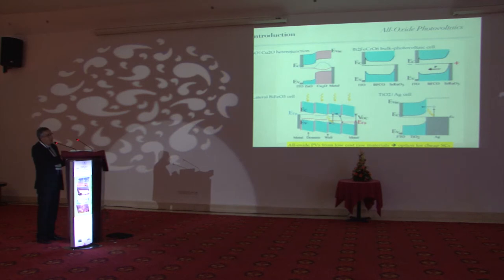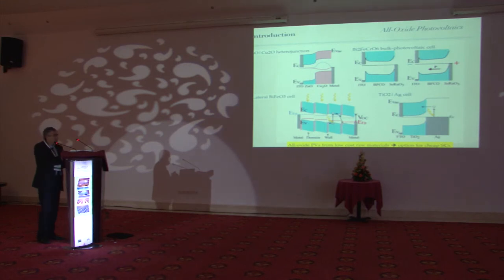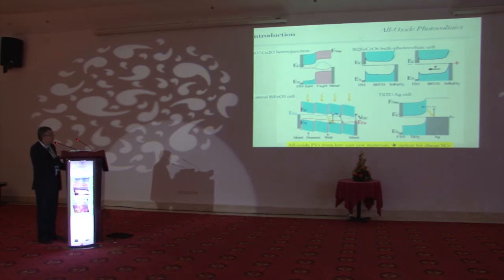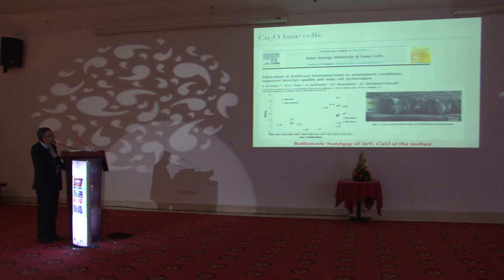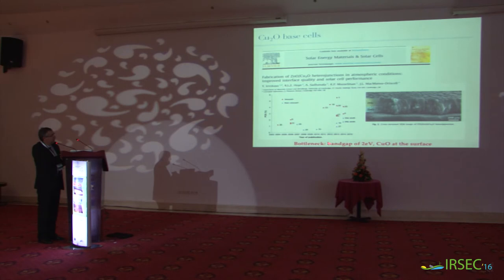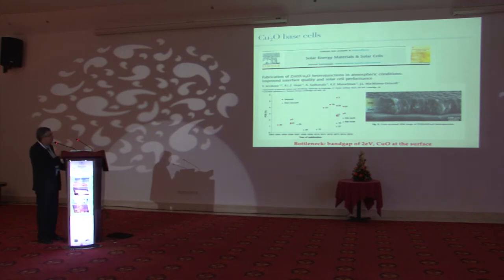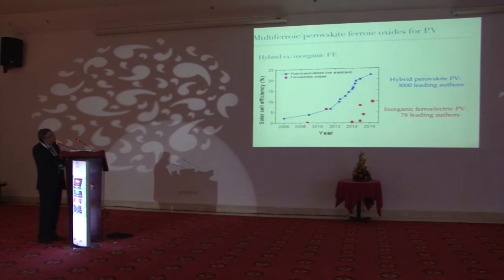There are sketches here concerning all-oxide photovoltaics, where the whole structure is made with oxides — for instance, zinc oxide with copper oxide, BFCO bulk photovoltaic cells, or BFO with TiO2 with silver contacts. All-oxide PV using low-cost raw materials is a good option for cheap solar cells. Looking at copper oxide, which has been thoroughly studied, its efficiency has been somewhat limited, with bottlenecks being its relatively high bandgap and the formation of phases at surfaces that limit performance.